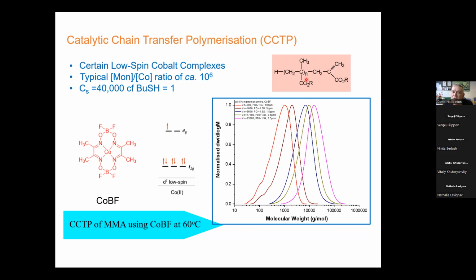And what it also does, I'm not going to go through the mechanism, but the way it works is that the majority of chains are initiated with a hydrogen atom, which comes from the cobalt, and the terminal end is a vinyl group. So our oligomers have got hydrogen, and they're just integral numbers of the methacrylate, and we have this vinyl group on the end, which is quite a special vinyl group. So these are the first RAFT agents.